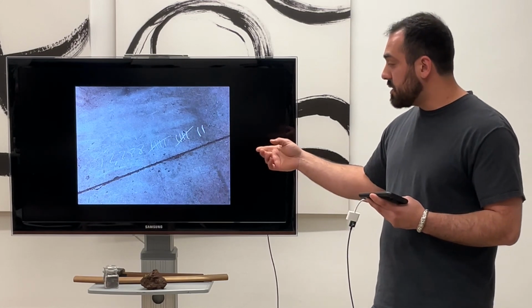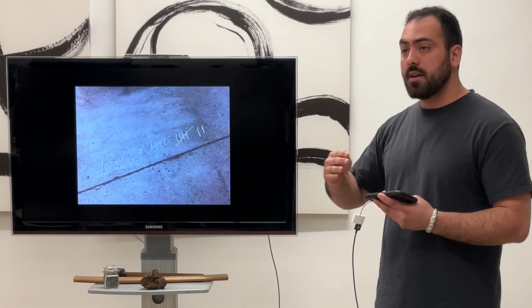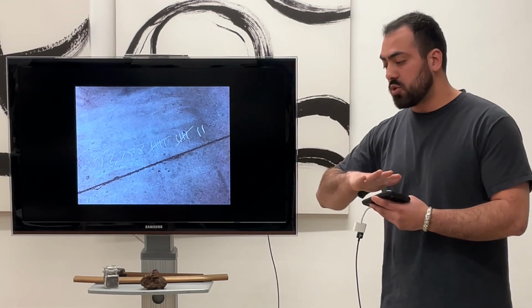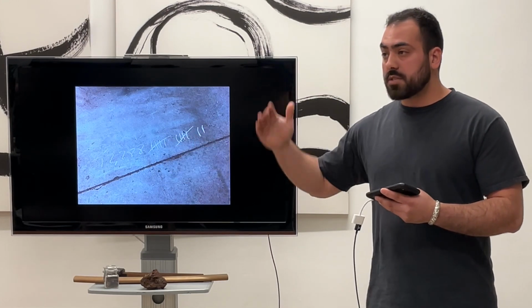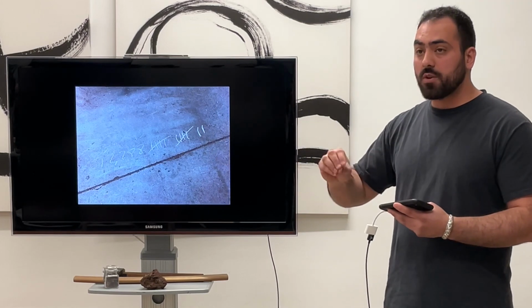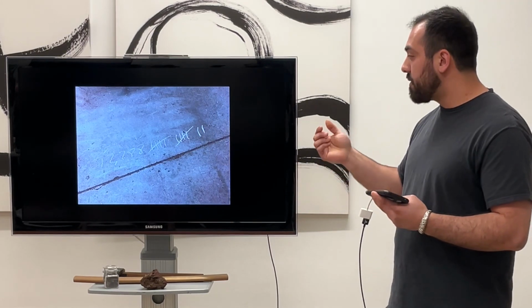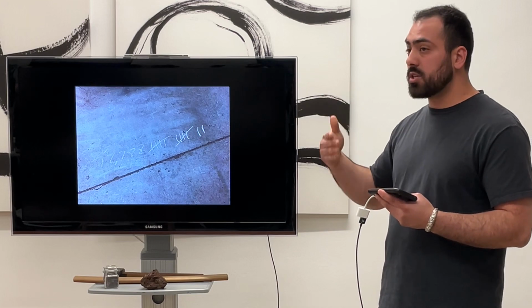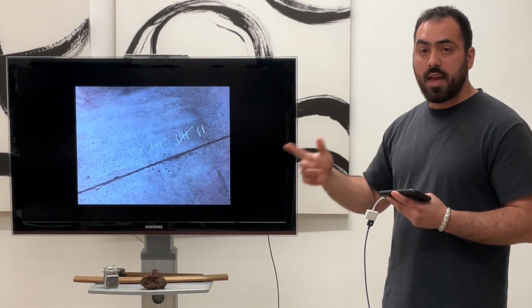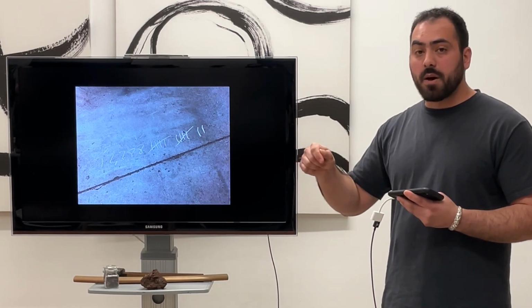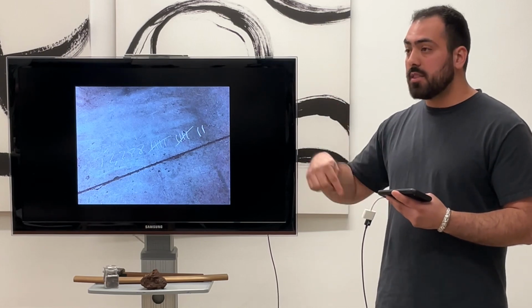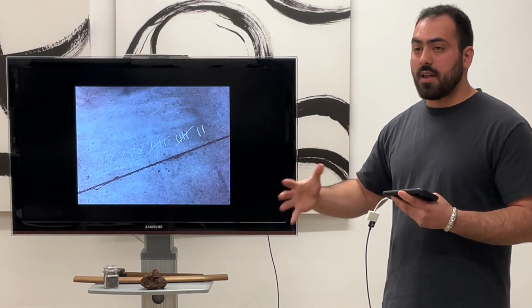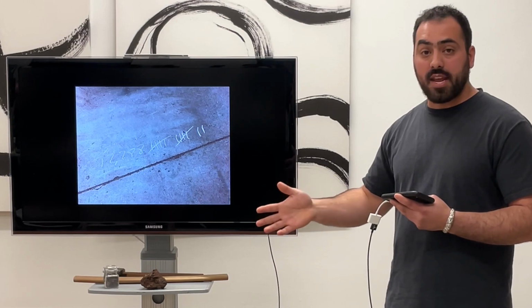One of the reasons is I'll often do a restack, where instead of just hot folding, I'll draw it out into a big bar, clean up the surfaces, cut it, and restack it, and then forge weld it again. The reason for that is I want to continue making sure that the material is clean on the inside as I fold. And if I find a bubble, I can cut into it, clean the inside of the material, flatten it again, and then forge weld it and get rid of that issue.